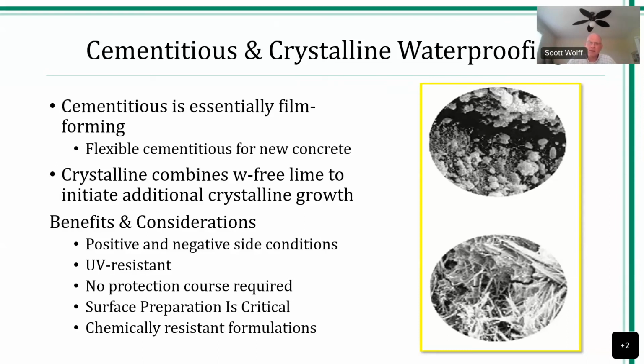So the Achilles heel to these types of systems is they obviously cannot be applied to expansion joints. They have limited elongation. If we have larger cracks, this is obviously not going to magically fill that in. And surface preparation is very, very important for the flexible cementitious or the non-flexible crystalline type systems. We typically require or specify minimum 5,000 psi to basically score the surface or open it up. Again, for the International Concrete Repair Institute, we have to have a CSP of minimum 3 to provide a good mechanical bond of these systems as they're being applied.